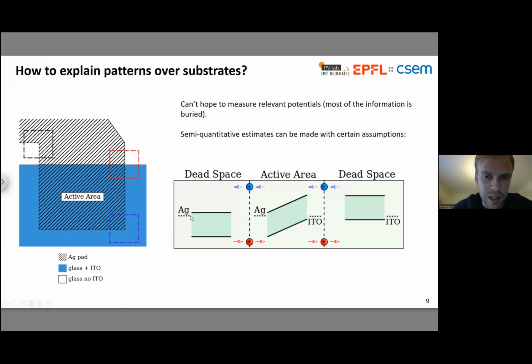Basically you draw these little simplified band diagrams in which you place the two electrode potentials at wherever they need to be. So here I'm doing a short-circuited device, so I put them aligned with one another. And then you pick the position of the perovskite bands accordingly. We know that we can get a reasonably good contact with silver, so that implies that the position of the perovskite bands is somewhere down here in this region of dead space, and we get a reasonably good contact with ITO, which means the bands are positioned somewhere over here in the other region of dead space. And then within the active area, we have this familiar PIN type band structure.